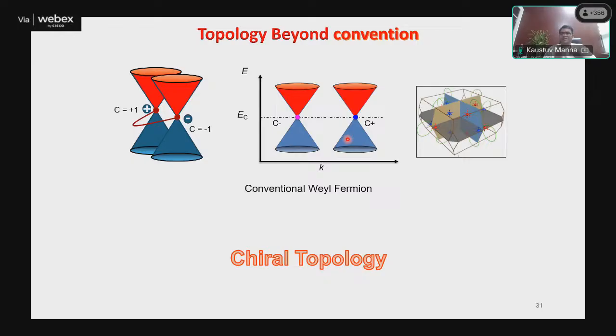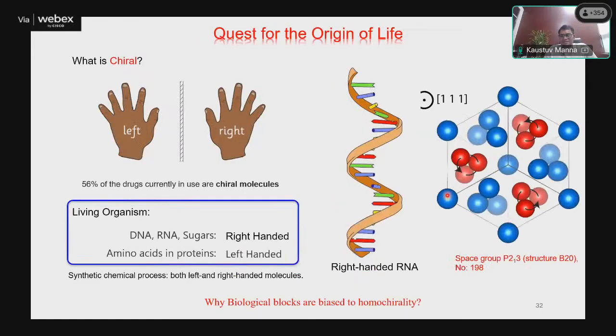So it is important that if you can shift one Weyl point with respect to the other, then you can probably lock one Weyl point compared to the other. You can independently see or map the response of one Weyl point with respect to the other. So here comes the chiral, because chiral means structural chirality. Instead of mirror symmetry, you have the glide operation, reflection plus translation. As a consequence, you see, this is the chiral topology.